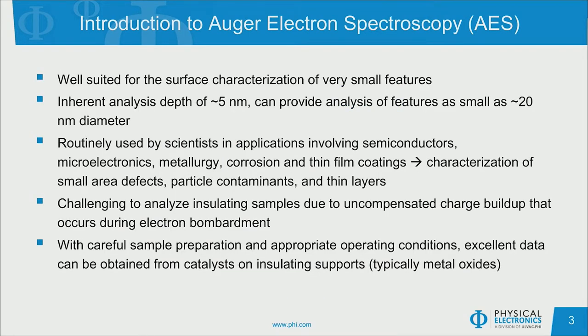AES is a well-suited technique for the surface characterization of small features. It has an inherent analysis depth of just a few nanometers, making it very surface-sensitive. It can also provide lateral resolution of particles as small as about 20 nanometers in diameter. AES is routinely used by scientists in applications involving semiconductors, microelectronics, metallurgy, corrosion, and thin film coatings, for the purposes of characterizing small area defects, particle contaminants, or thin layers. One of the challenges of AES is analyzing insulating samples, due to the uncompensated charge buildup that occurs during electron beam bombardment. However, with careful sample preparation and appropriate operating conditions, we can collect excellent data from things like catalysts on insulating supports, typically metal oxides.